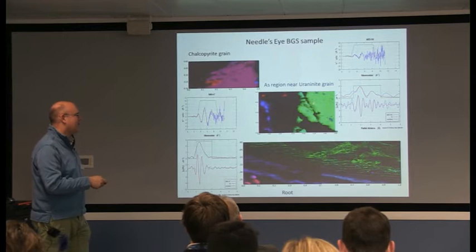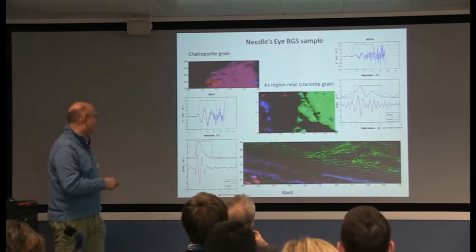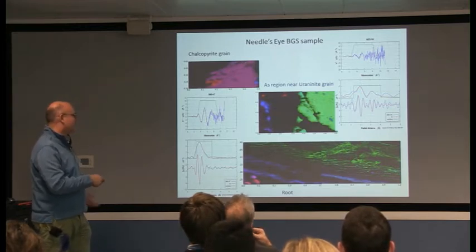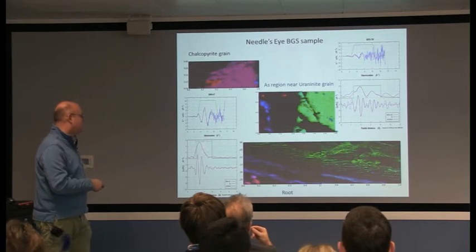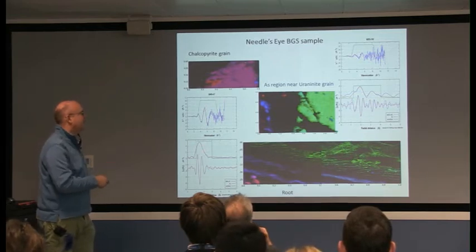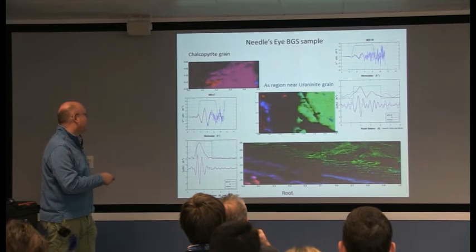The uraninite grain is not very interesting. It turns out to be uraninite, which isn't very surprising, but we could tell the oxidation state, and this was a uranyl type group on the side of the arsenic.